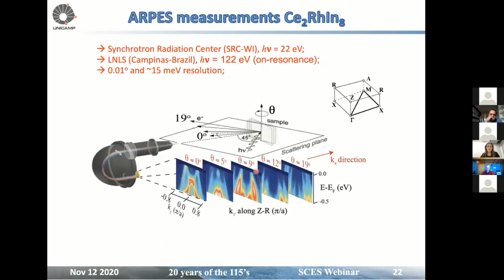So the measurements were, I just realized that the low energy measurements were done at the already closed Synchrotron Radiation Center at Wisconsin, and the on-resonance measurements were done on the Synchrotron Light Source in Brazil that was already closed. So I found it funny. But anyway, for the low energy measurements, that was our best resolution case. It's about 15 meV resolution, and that will be important to show the next results. But that is how we get data from ARPES.